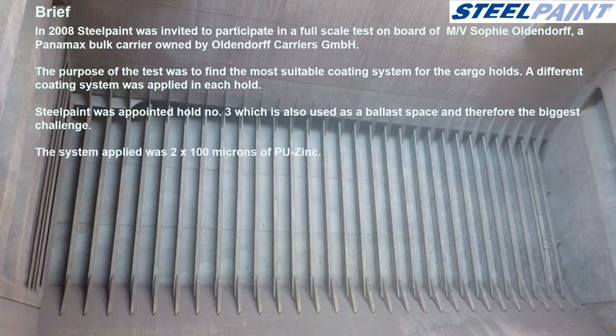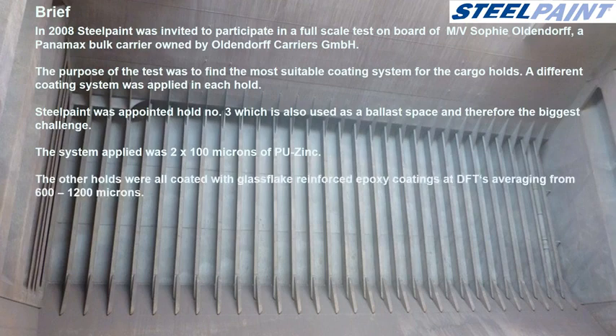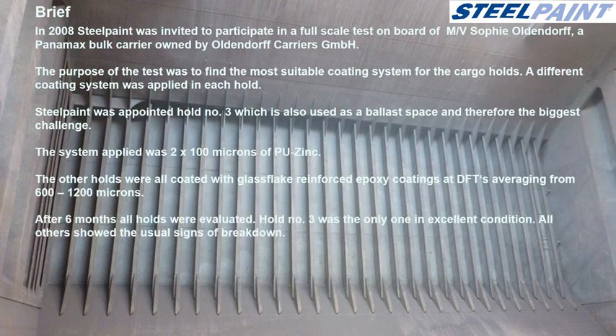The system applied was 2 times 100 microns of PU zinc. The other holds were all coated with glass flake reinforced epoxy coatings at DFTs averaging from 600 to 1200 microns. After 6 months, all holds were evaluated. Hold number 3 was the only one in excellent condition. All others showed the usual signs of breakdown.